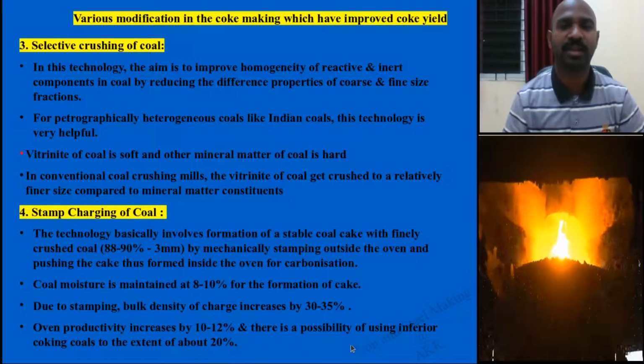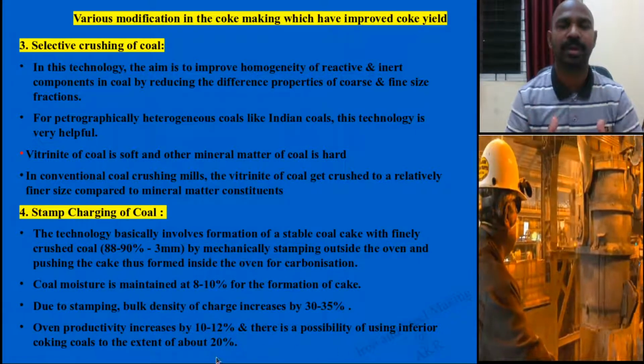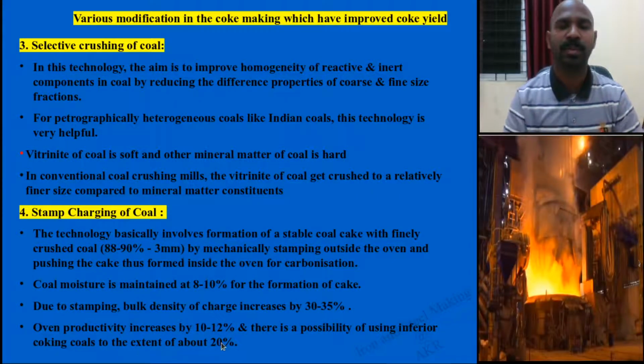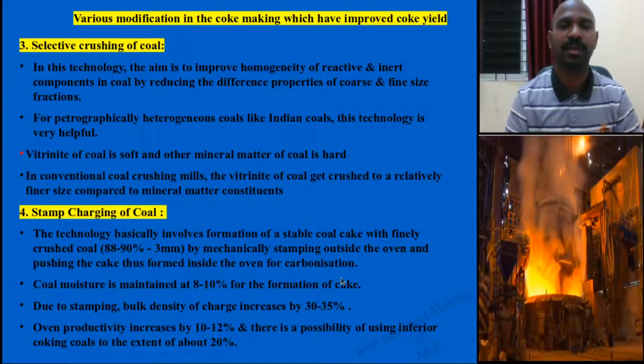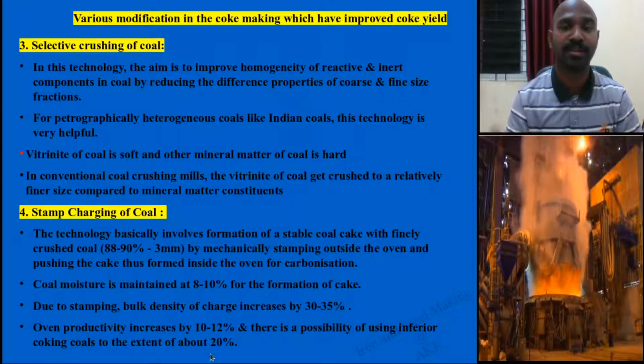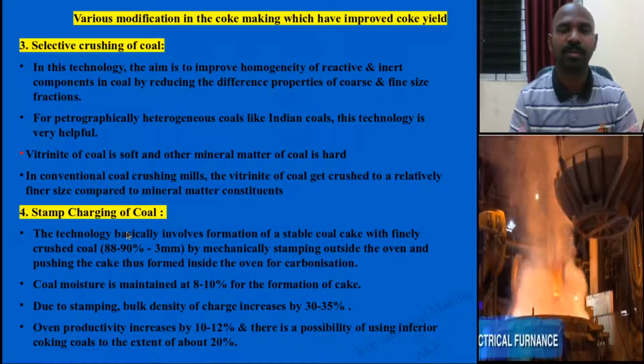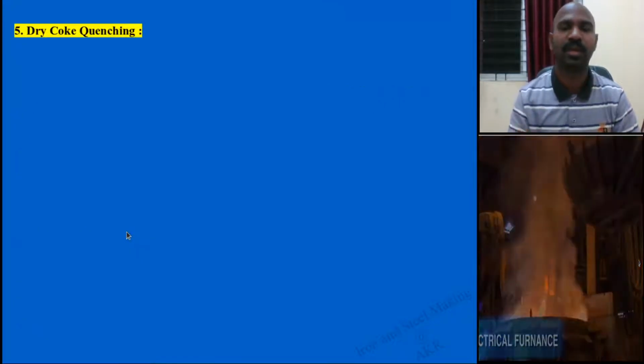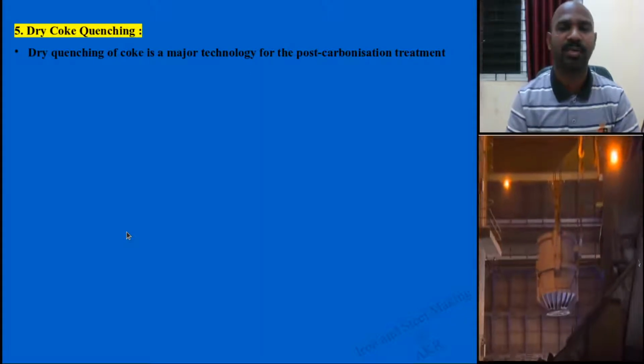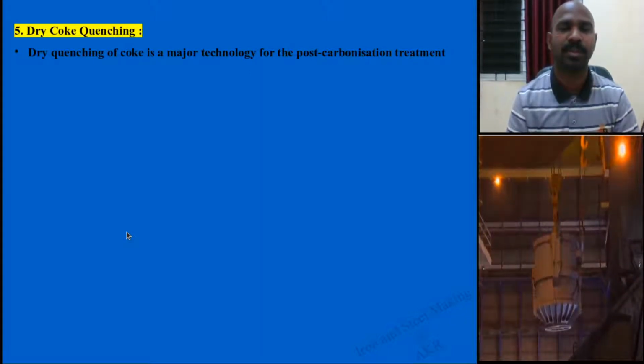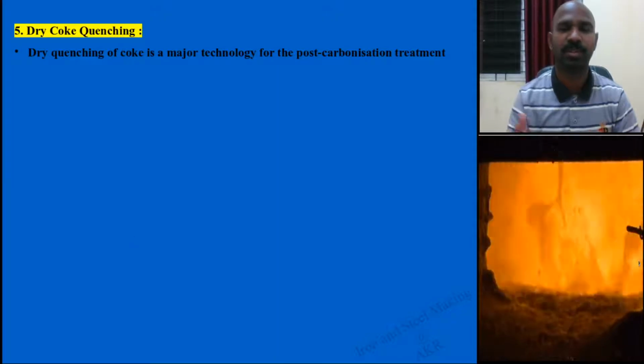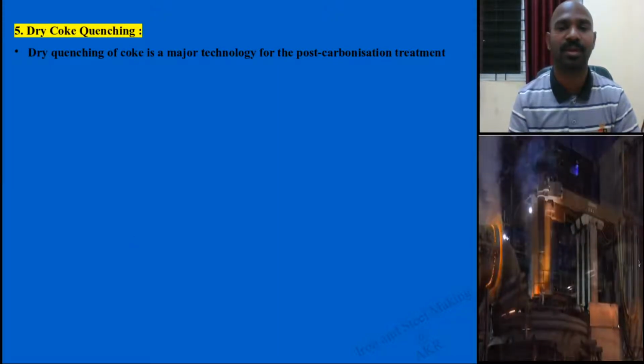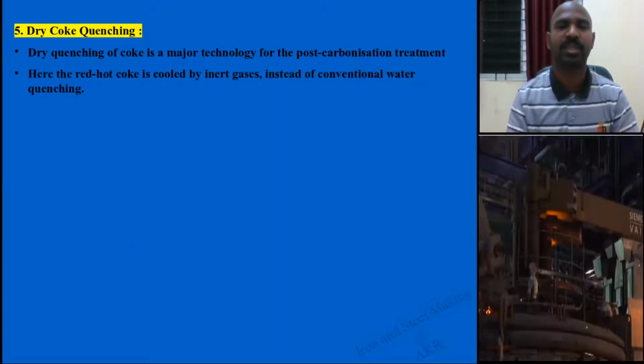And poor coking coal can also be incorporated when you include the stamp charging step. About 20% of coal with poor coking characteristics can be included. A combination of fine size and coarse size can also be included. That is another addition. Another technology, a post-carbonization technique, is dry quenching, dry coke quenching.